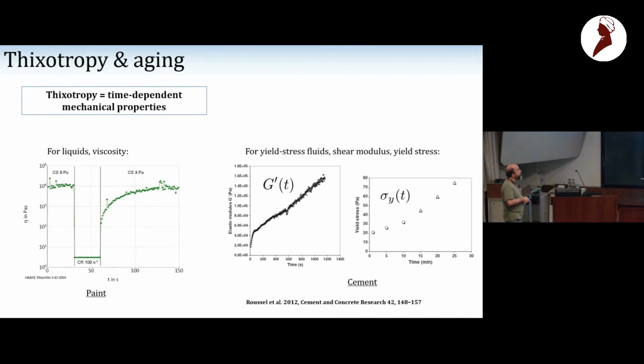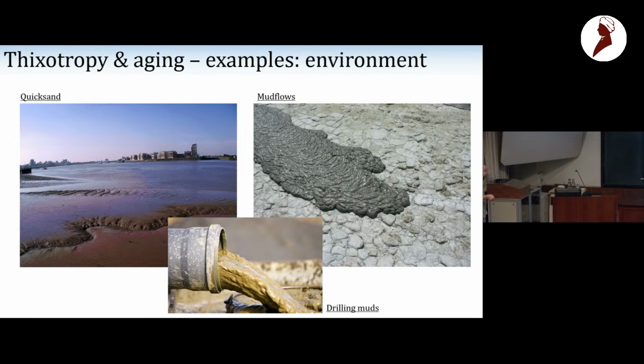And it's a material that does show aging. If you take a cement paste and you just put it at rest, you will see that the modulus ages logarithmically, the yield stress ages logarithmically. And if you read in textbooks on thixotropy and aging, there are many other materials where you have this. Rheological textbooks have been very much inspired by all the experiments that people have done on colloids and the analogy between colloids and glasses. And so if you read in textbooks, people tell you that this thixotropy and aging has a structural origin. It's just the same thing as we saw before with molecular glasses, and maybe the structure there is some slowing down of the aging dynamics.